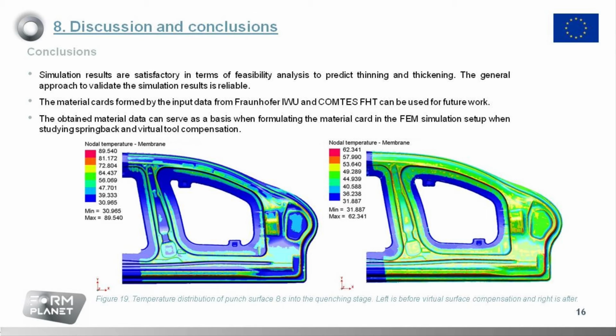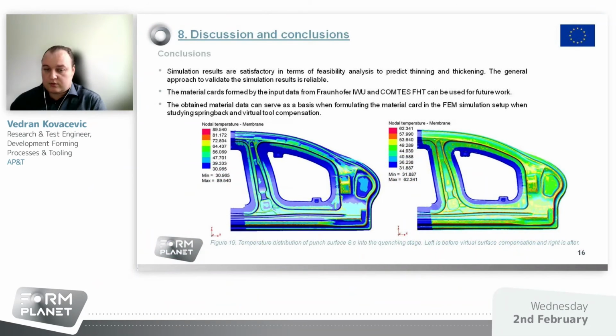And as seen in the image, it is quite clear that the contact after the virtual tool surface compensation is better, as the temperature distribution on the tool surface is more even. The next step would now be to investigate the impact on springback after the virtual tool compensated surfaces in the simulation.